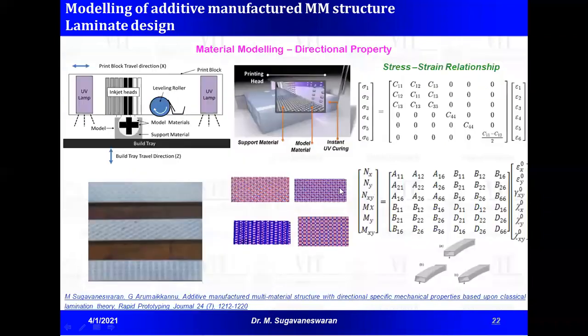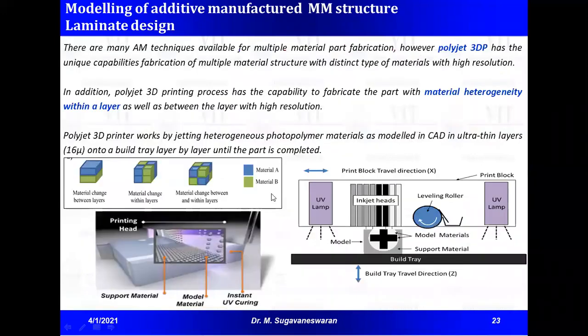So based on this CLT relationship, the secondary material is designed into the primary material, and this structure, as well as the previous structure I have discussed, is fabricated through a PolyJet three-dimensional printing process from Stratasys, which has a droplet of photopolymer deposition that is cured immediately with the help of a UV lamp layer by layer, and you have an inkjet ejection mechanism to eject multiple materials within a layer.